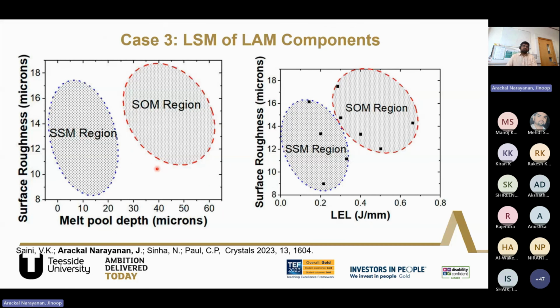So we could generate a lot of correlation with respect to the melt pool depth and surface roughness, and we could also correlate the energy density with the surface roughness, and we could divide the regions into shallow surface melting and surface over melting, and we could clearly identify which region we need to focus, or which energy density we need to focus on to get a desired surface quality.